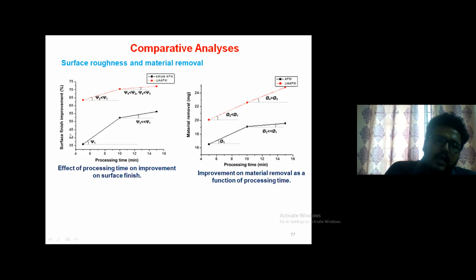So here you can see the surface finish improvement on the y-axis and the processing time on the x-axis, right? This black line shows the simple AFM result and the red shows the UAFM result. What we observed is that by processing up to 15 minutes using simple AFM, we achieved 55% improvement in the surface finish when comparing before and after, right? Whereas by using ultrasonic frequency, at 5 minutes itself, we achieved 63% improvement of surface finish, and we went up to 75% improvement in the surface finish.